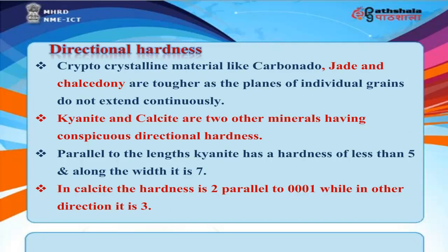Cryptocrystalline material like carbonado, jade and chalcedony are tougher as the planes of individual grains do not extend continuously. Kyanite and calcite are two other minerals having conspicuous directional hardness. Parallel to the length, kyanite has a hardness of less than 5 and along the width it is 7. In calcite, the hardness is 2 parallel to 0001, while in other directions it is 3.